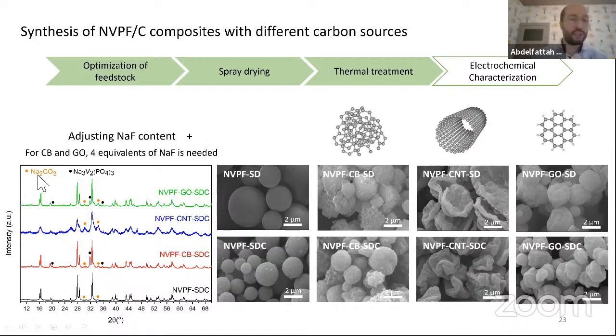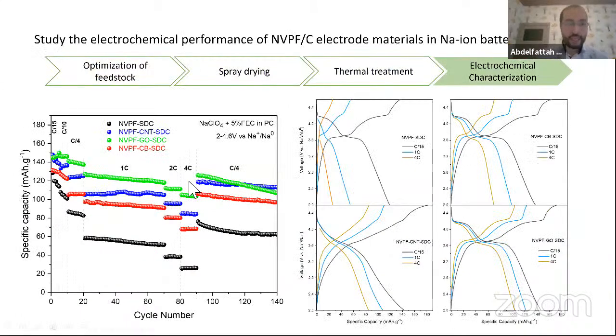We have, as I mentioned, only this sodium carbonate that we remove easily by grinding in water. We can see here, by comparing the electrochemical performances by carrying out the rate capability test, that the one with graphene showed the highest capacity at all rates, which means that graphene increases the electronic conductivity much better than the 2 other carbon sources. We can see, for example, at 1C, we have almost the theoretical capacity of the NVPF material.